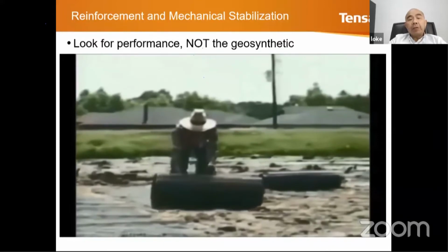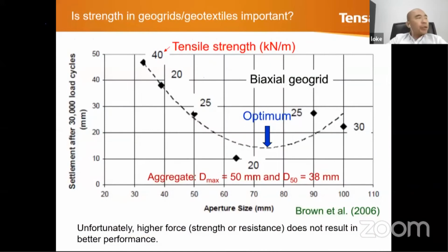So you can see the difference. One with the geotextile, which is very high strength, but very poor stiffness, and you can't work at all. The other one is a geogrid, which has got lower strength than the geotextile, and you can see that it works perfect. Why? Because again of stiffness. Okay, so is strength important?